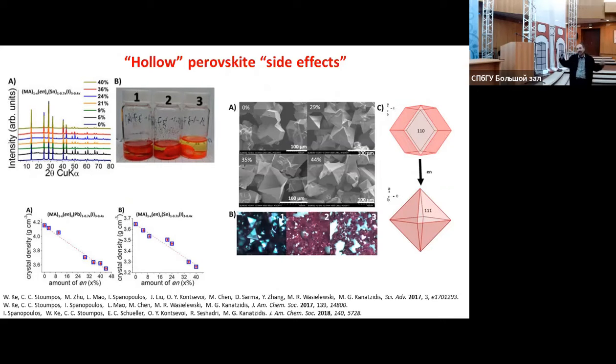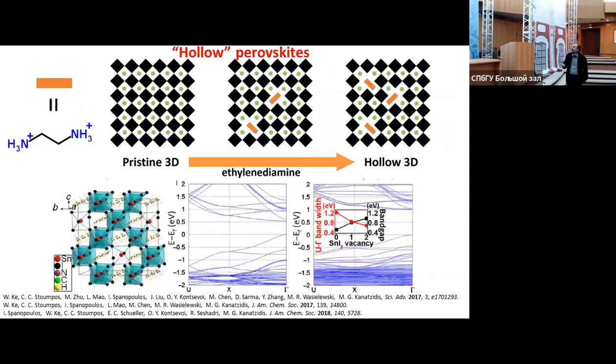But the most compelling experiment, from my point of view, is that if you actually measure experimentally the density of the crystals that you produce, you see that there is a very significant change in the density. So a normal density is around 4 for the perfect perovskite, and then you can end up with a density of 3.5. So the organic cation goes in. Where? We're not sure yet. And we're not sure exactly what goes out, because it's impossible. The charge, remember, the charge is 2+, as opposed to the A-site cation, which is 1+. So something must go away.